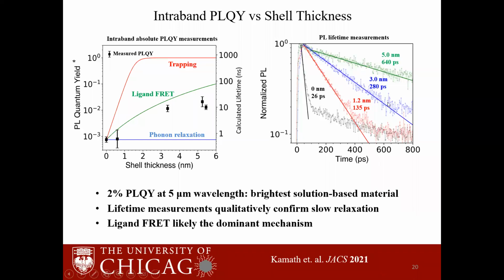But more importantly, the fact that we see this increase tells us that phonon relaxation was not the bottleneck for our core quantum dots. So this tells us that if we want to make more sensitive thermal cameras at room temperature, we need to find a way to slow this ligand FRET mechanism. So this was the first part of my talk.